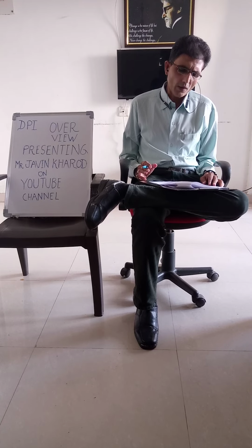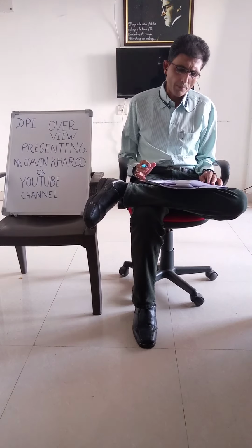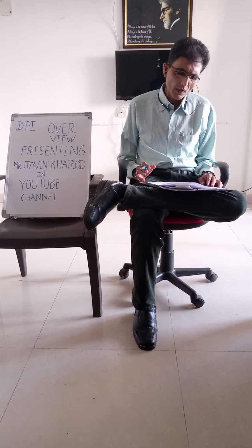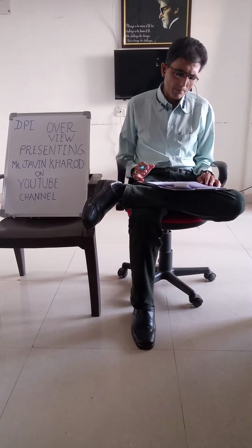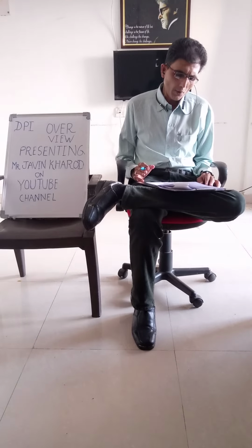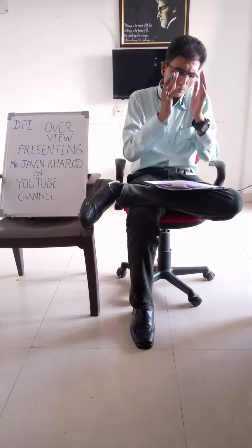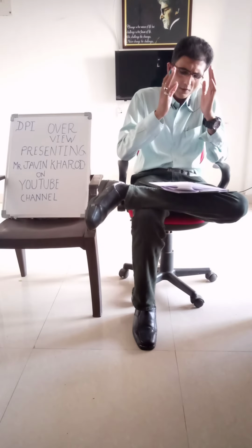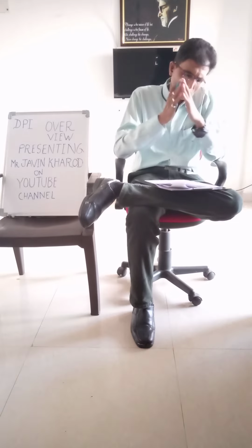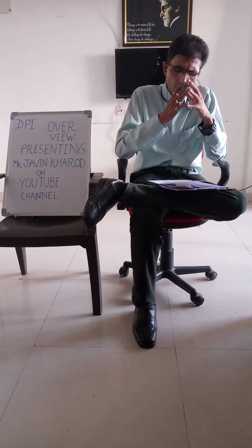When using non-aqueous developer or dry powder, the sample must be dry prior to application, while soluble and suspendable developers are applied while still wet from the previous step. Commercially available aerosol spray cans may be employed, with acetone, isopropyl alcohol or a propellant, or a combination of the two. Developers will be semi-transparent and coat the surface. The developer draws penetrant from the defect out onto the surface to form a visible indication, commonly known as bleed out.